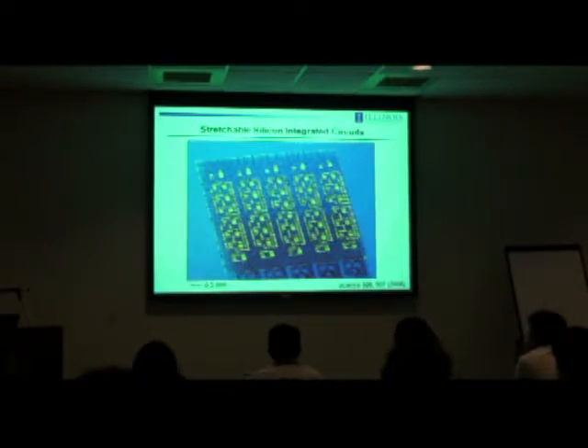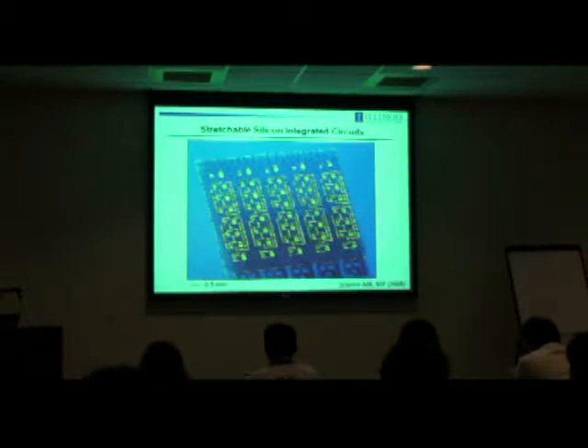So this is supported on rubber substrate. You can see the wrinkles and the wavy nature of this ultra-thin circuit. The photographer who took this is actually illuminating the circuit to highlight that kind of out-of-plane deformation due to the illumination angle. So what we're seeing here is the troughs appear black, and the raised peaks in these wave structures appear bright, just due to the way the light is reflecting. So it makes it look as though this thing has been deformed at a level that's a little bit more extreme than it actually is.